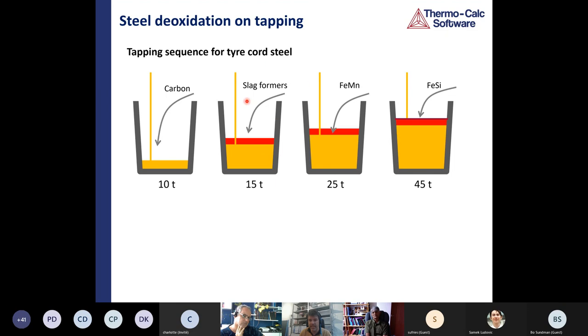And by the way, also the slag formers, adding these before deoxidizing is a very bad idea, because then the steel will still have high oxygen potential and the slag won't be active, won't desulfurize the steel as we've seen previously. So there's a strict sequence of when these alloys are being added, and there's a reason for that. Having a kinetic simulation allows us really step by step to simulate what's happening in function of these two minutes during this tapping procedure. There are other things that are happening, and I'll be talking about these as well.